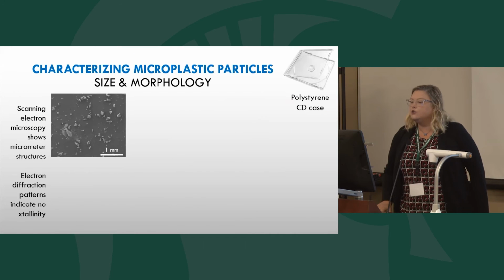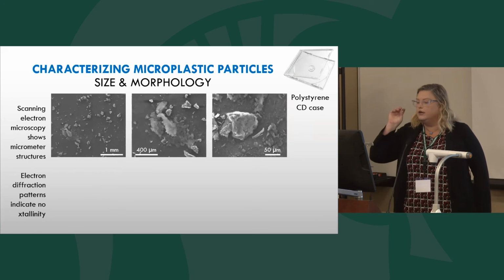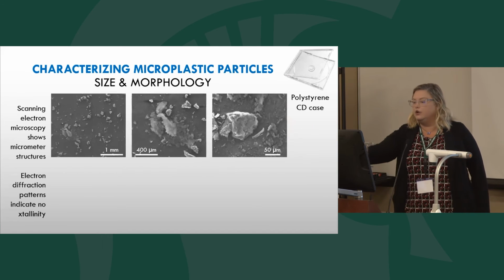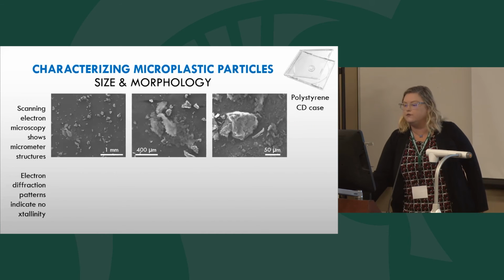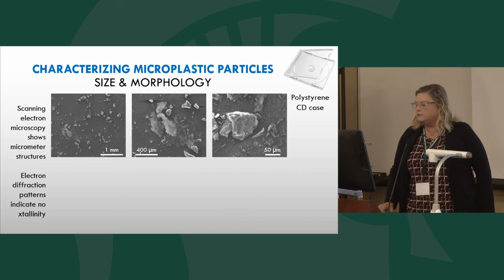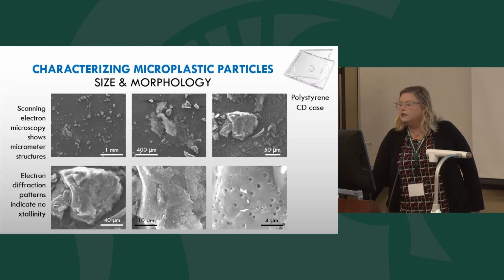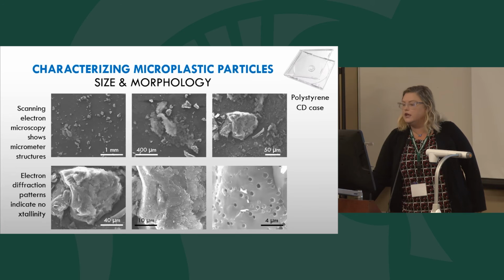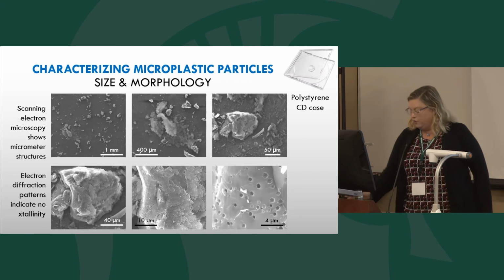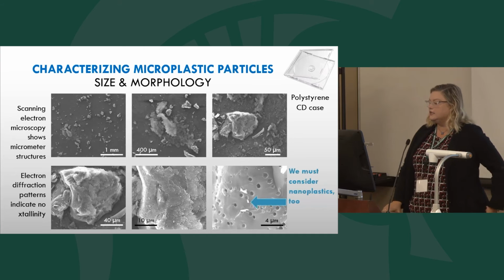And when we characterize these microplastics, if you increase the magnification on each of these images, with lowest magnification here and then highest magnification down to here, not only are we seeing the heterogeneous nature of these surfaces over the different magnifications, but we start to see these really cool little pit formations here that are really interesting sites for which maybe other things can hide inside of.